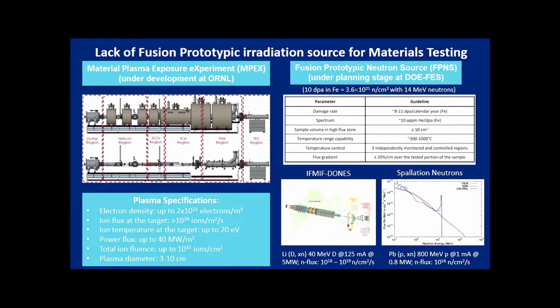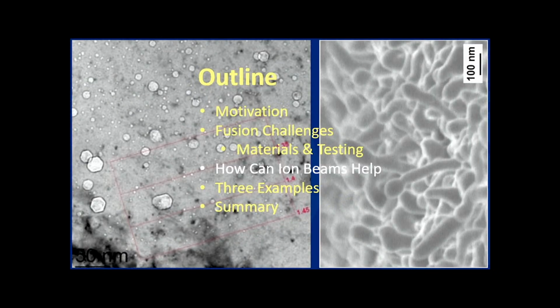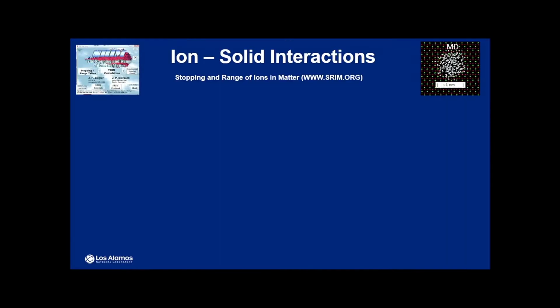Obviously, there are some neutron capabilities available at Los Alamos and Oak Ridge for the spallation neutrons, but there are some concerns regarding the spectrum impact, because of the much higher energy neutrons in the spallation neutron source and also the much higher yield of hydrogen and helium gas production. They're not very typical of the 14 MeV neutron. So how can the ion beam help? Obviously, it depends on how we use the ion beam in the materials process. Ion beams have been around for a long time.